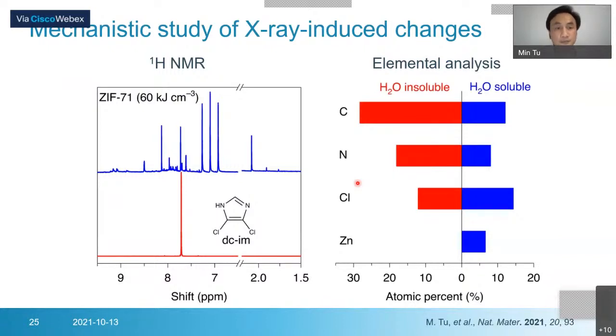And then we did some mechanistic study of these X-ray induced changes. The first idea is to do NMR measurement. So we have this dichloroimidazole. We see it has only one proton here, around 7.7. After X-ray exposure, we see many peaks, which makes it very difficult to resolve which components we have after the X-ray exposure. But one point we are very sure of is we have many different products.